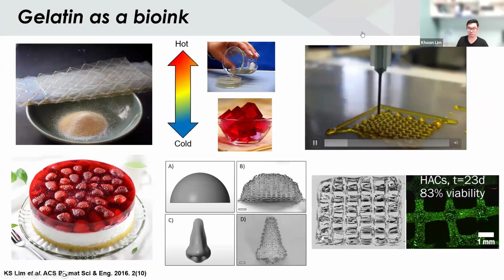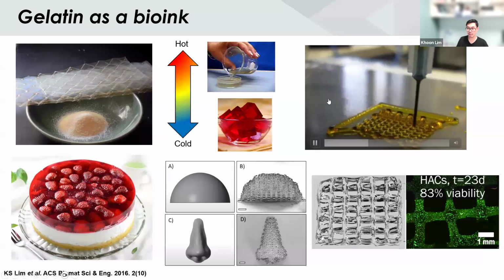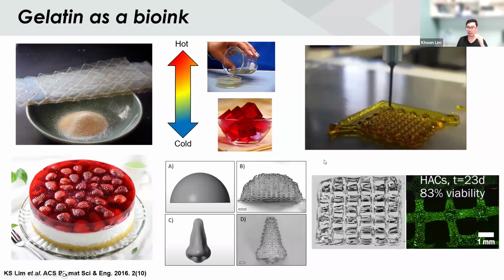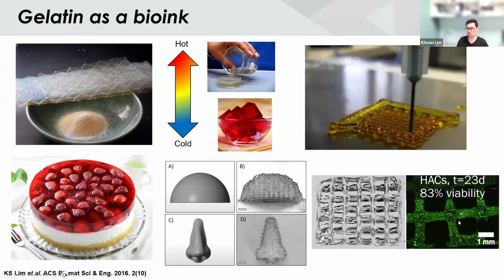So you can just imagine with this syringe, I can control the temperature of the syringe. I can heat it up to 30 degrees, so it will become a solution. But I can also cool down this base plate to 20 degrees. So the moment this solution is pushed out and touches the base plate, it will solidify as a physical gel, and then you can start stacking them layer by layer. This process itself is also quite safe with the cells. You can see here we have put primary human articular chondrocytes and cultured them for more than 3 weeks, and the cells stay quite highly viable. So this shear thinning process, or using shear force to push these bioinks having cells within them, is often quite cytocompatible to the cells. So you can start making anatomical constructs like this, for example, of the whole human nose, and that works quite well with gelatin.